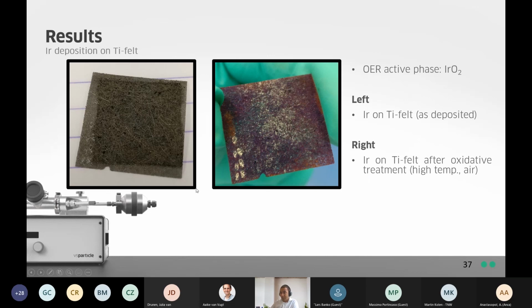So these iridium nanoparticles were deposited on a titanium felt. We see that here on the left. This is what the material looks like directly after deposition. But for the oxygen evolution reaction, you need the oxidic phase of these iridium nanoparticles. So on the right, we show you the image of a calcined material. It was calcined in synthetic air at high temperatures, and it shows you that the material is quite stable.